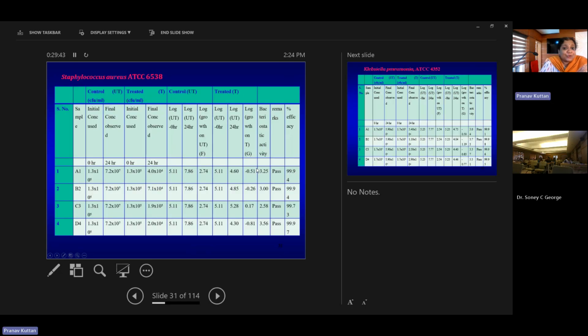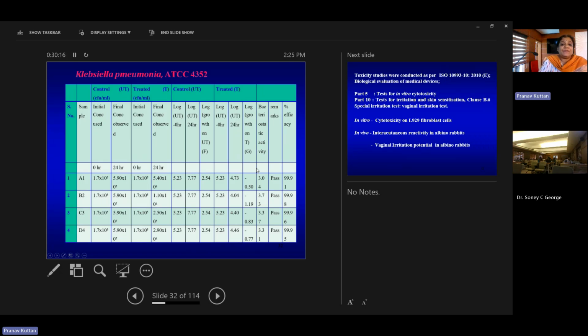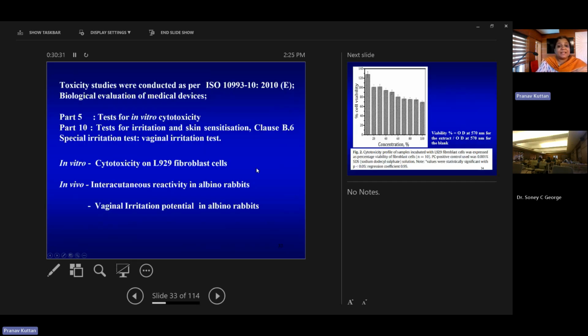And this is the JIS L1902 method, which was done on Staphylococcus aureus. It was done using 3 different concentrations. The criterion for passing this test is that the bactericidal activity, when calculated, should be more than 2. For all the concentrations, it was found to be more than 2. Hence, this material passes the antibacterial activity test, and it is found to have a percentage efficiency of greater than 99%. The same thing was found with Klebsiella pneumoniae. Here also the bactericidal activity was more than 2 and efficiency was more than 99%.